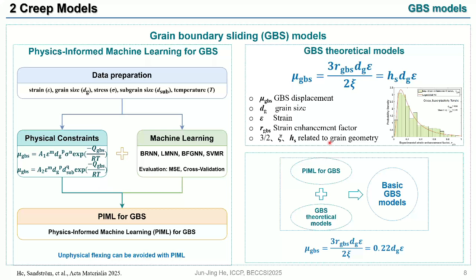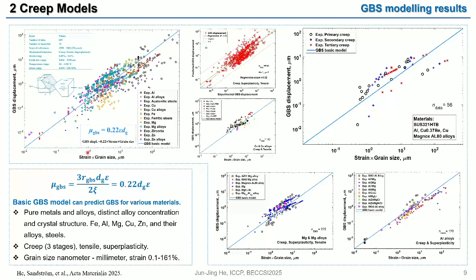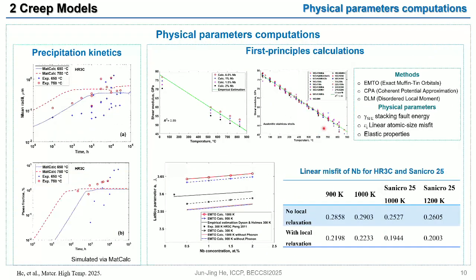Here are the results for the grain boundary sliding models. Now we can see that the model can predict the grain boundary sliding for various materials and also covers many different conditions. In addition, it can also be applied to the three creep stages: the primary, secondary, and the tertiary creep stages. On the other hand, for the physical parameters in the basic creep models, we use MatCalc to simulate the precipitate evolution, such as the particle radius and the phase fraction as a function of time in Sanicro 25 steels. And also with first principles methods, we used the EMTO code to calculate the physical parameters like the elastic properties and the lattice misfit.